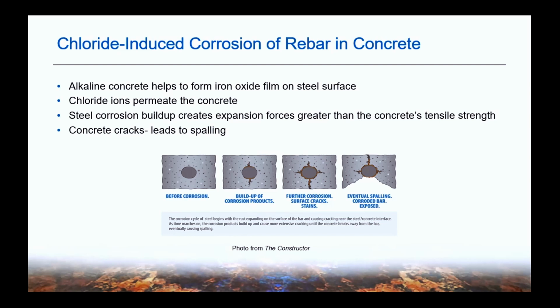But if that concrete doesn't have barrier protection, or you don't have cathodic protection employed, you can end up having those chloride ions permeate that surface. And what happens is they end up getting to the steel rebar. And as you can see diagrammed here, over time, it's going to cause that steel rebar to corrode. Concrete, because it is low in tensile strength, as that rebar expands with corrosion products, it's going to end up causing cracking, spalling, and in some cases, complete failure.